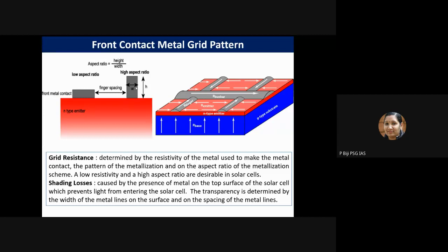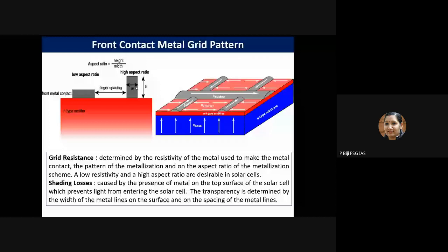Then the second parameter is the shading loss. Already we have mentioned that the front contact metallization contributes majorly towards the shading loss. This is caused by the presence of metal on the top surface of the solar cell, the fraction of the top surface covered by metal, which prevents light from entering the solar cell. The shading loss is determined by the transparency of the top surface. The transparency is determined by the width of the metal lines on the surface and the spacing of the metal lines, which I have already mentioned. And again, an important practical limitation is the minimum line width associated with the particular metallization technology.